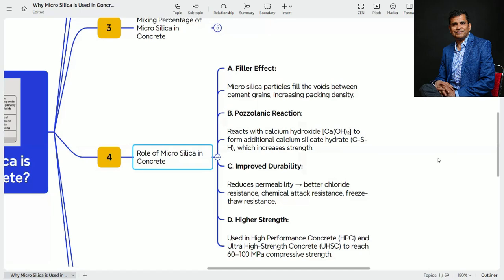But here, what is happening? First, C3S, when it starts reacting with the water, produces the CSH gel, which gives the strength. But whenever this reaction is happening, it produces 3 molecules of calcium hydroxide. Now, what is the use of this calcium hydroxide? It is of no use. This calcium hydroxide reacts with the water and becomes soluble, and it makes the concrete porous. And if the concrete becomes porous, harmful chemicals like chloride, sulfur and carbon dioxide will penetrate inside the concrete and corrode the steel, as well as deteriorate the concrete itself.